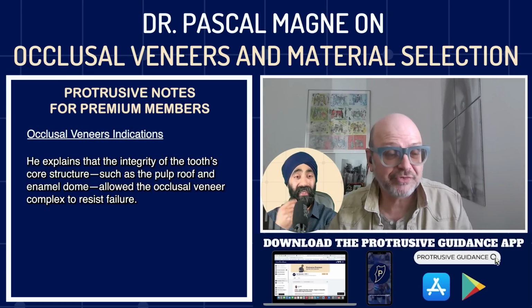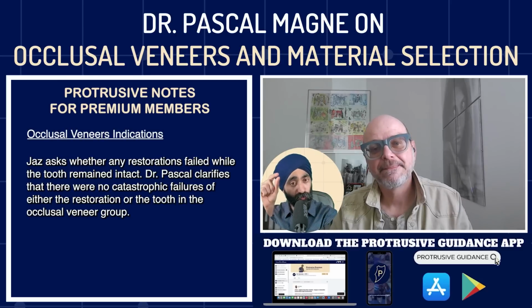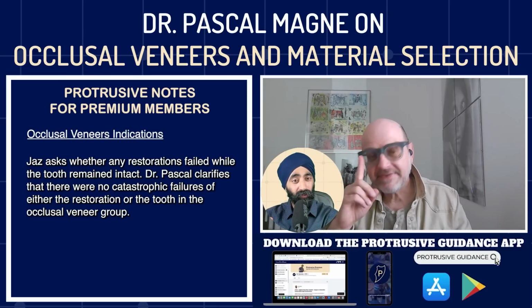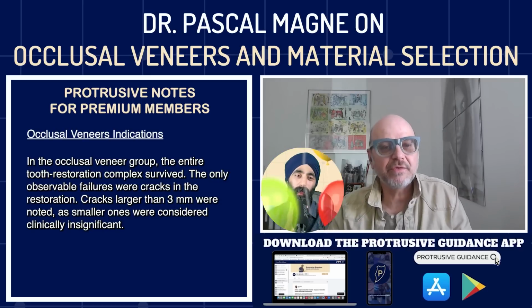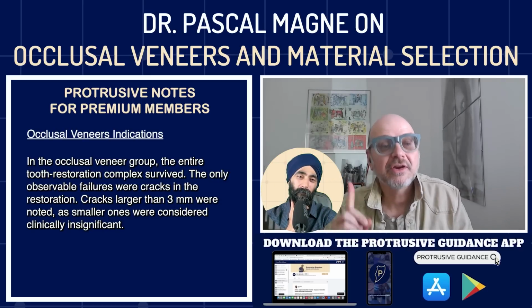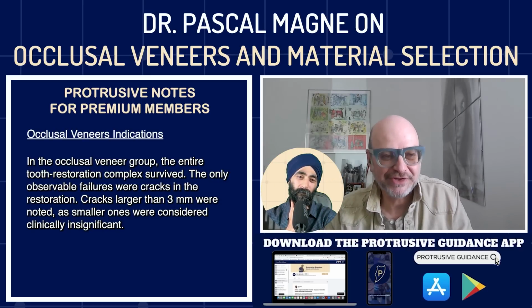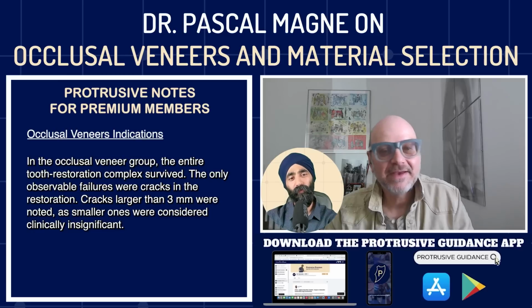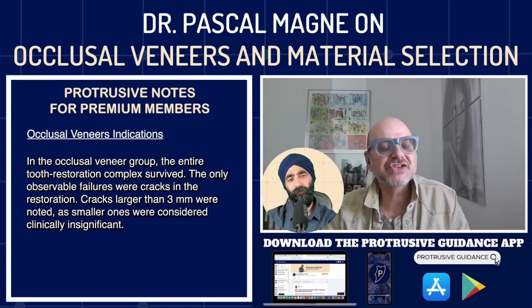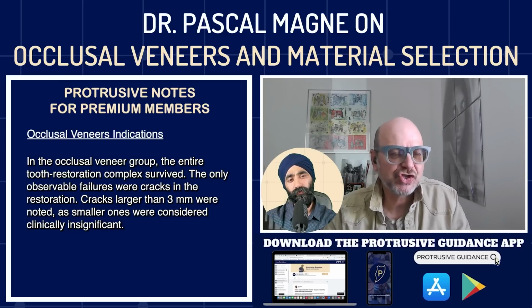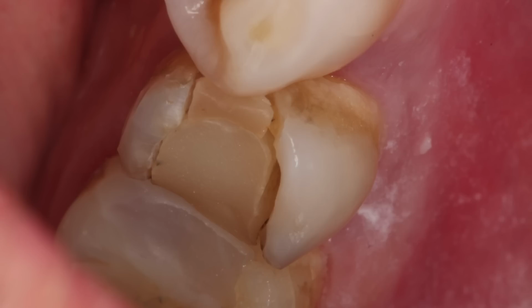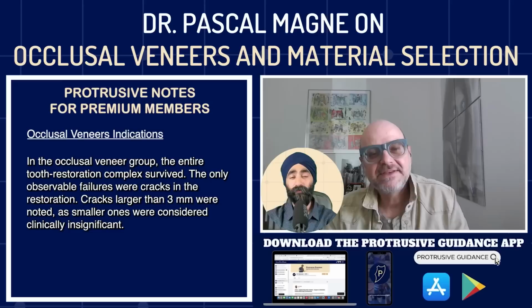The only thing we observed... That's why I wanted to ask. I was saying, did the restoration fail, but the tooth survived? But you're saying that actually the entire complex survived. The entire complex survived. The only thing we were observing was cracks in the restoration. And we always considered the cracks more than 3 millimeters, because less than 3 millimeters, really nobody will see them necessarily. Okay?